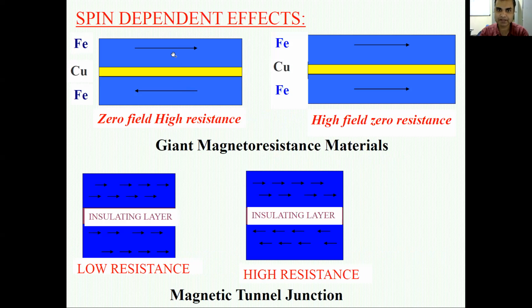We know that iron is magnetic in nature. So when their magnetization directions are opposite to each other and they are separated by this spacer layer, which is copper, then they have high resistance in zero magnetic field. But if you apply a magnetic field so that this magnetic moment changes its direction to parallel to the upper layer, then in that case you will have low resistance at high field. This type of material is called a giant magnetoresistance material. Just by controlling the spin orientation, you are controlling the spin state. So that means there is a coupling between the magnetic property as well as the resistivity property of the system.